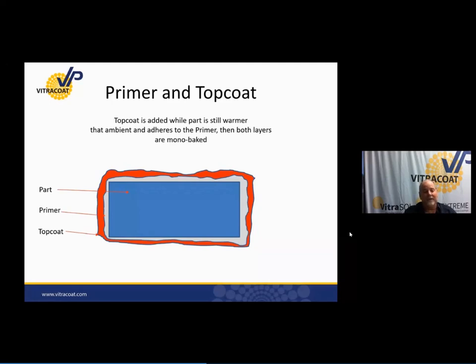Not to mention that I can define and design that primer to do things that my top coat may not be able to do. As I mentioned earlier, hang on edges because of the way it flows. Give me better adhesion characteristics because it may be an epoxy system. And then my top coat gives me my physical and aesthetic appreciation. I get the look and I can get the physical characteristics that I'm looking for in the top coat. So a 1 coat 4.5 mil will not give you the same protection as a properly applied 2-layer system.